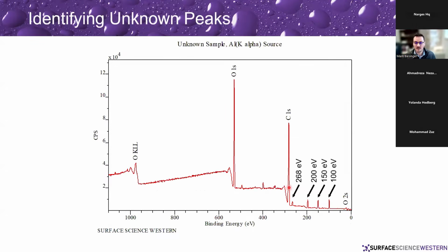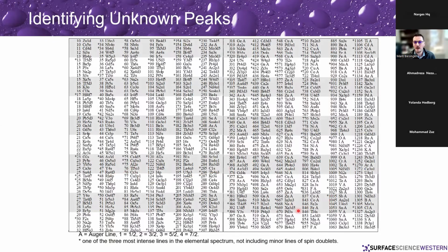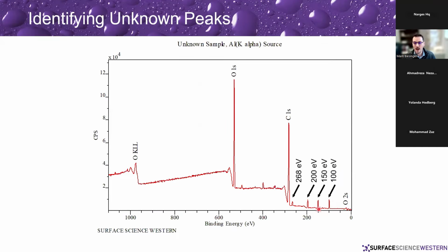If you have an unknown sample, you want to go through and look at the various peaks that are present, look at the binding energy of those peaks, and figure out what these are. There are tables and things like that that you can go through to pull out what elements should be there. A lot of the time, if you have, say, a silicon 2p peak, you also have to have a silicon 2s peak. So if you only have that one peak, then it's not silicon. It's got to have both peaks present.